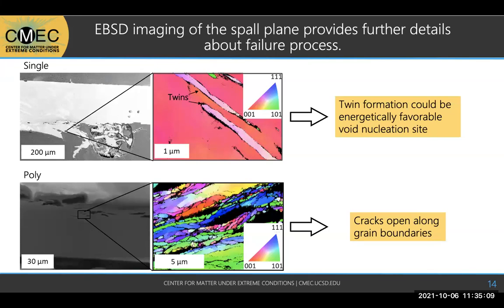So these are more post-shock characterization. I did EBSD imaging of the spalled plane. So this is electron backscatter diffraction. And in the single crystalline, I found these really, really nice twin boundaries, or what we thought were twin boundaries. I'll tell you in a moment that they really are. And so that goes back to that drawing I showed earlier where I said twin boundaries are probably energetically favorable void nucleation sites because of their weaker bonding and higher interfacial energy. And so we were really interested in these boundaries. And then in the polycrystalline sample, you can see in the bottom left image, there's a bunch of small crack opening locations. And when we do the orientation map, you can see that those cracks open right along grain boundaries. And so that also ties back to grain boundaries and twin boundaries being important. Next slide.